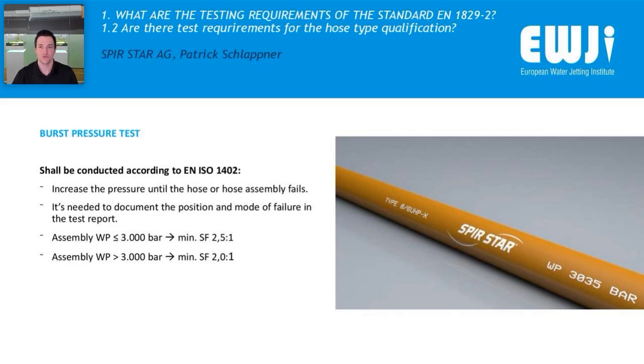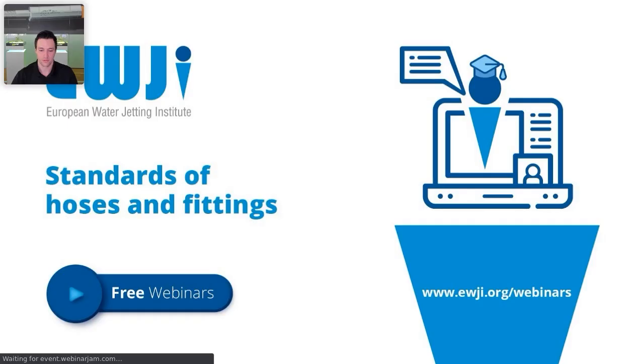For hose lines with maximum allowable working pressures up to 3000 bar, the safety factor, as I already said before, is 2.5 to 1. In hose assemblies with a working pressure over 3000 bar, the safety factor has to be 2 to 1. Here you can see a small animation of a bursting hose.